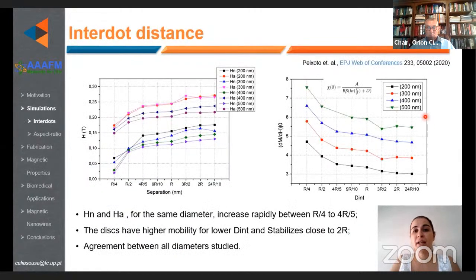The nucleation and the annihilation fields increase when we increase the distance between the nanodots, or the separation between the nanodots, up to 2 times the radius of the disk. A stabilization of the magnetic susceptibility value is also observed for the same value of interdot distance. So, for an interdot distance higher than 2 times the radius of the nanodisk, no interactions between the nanostructures influence the sample behavior, independently of the dot size.